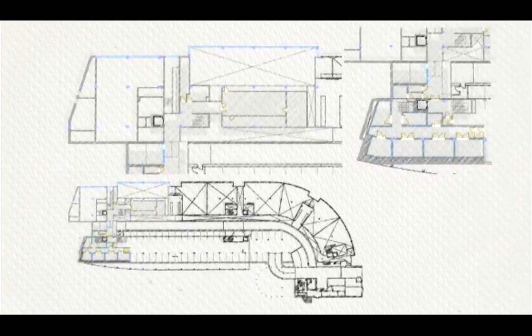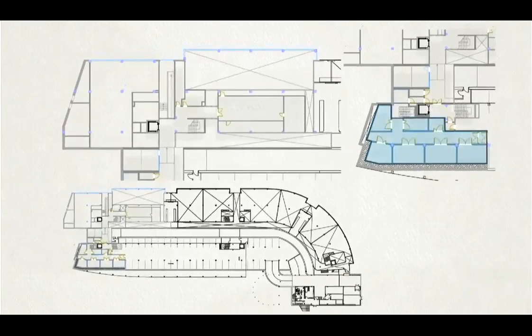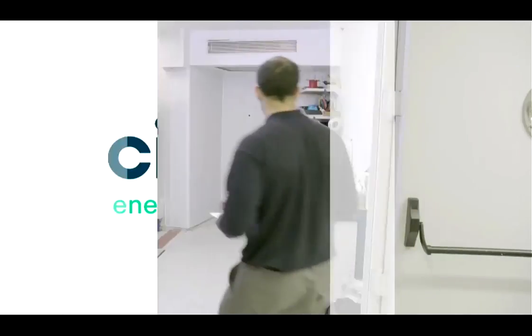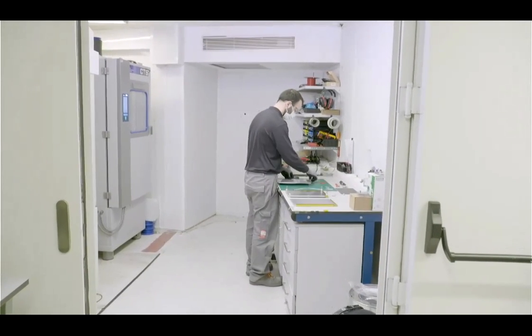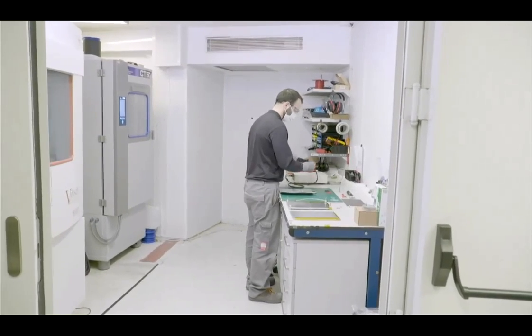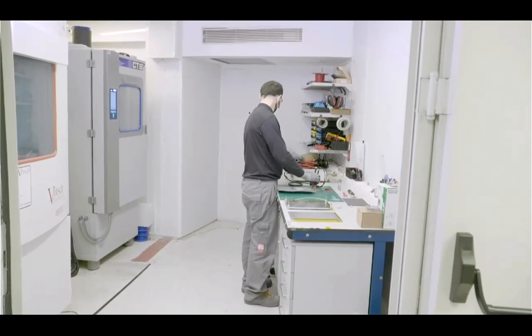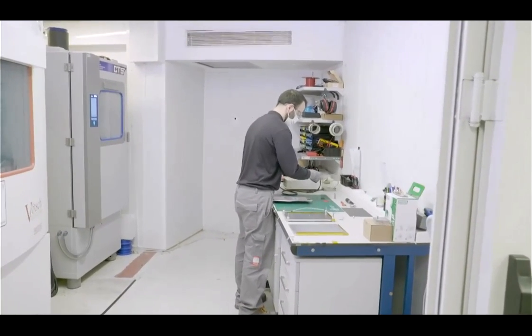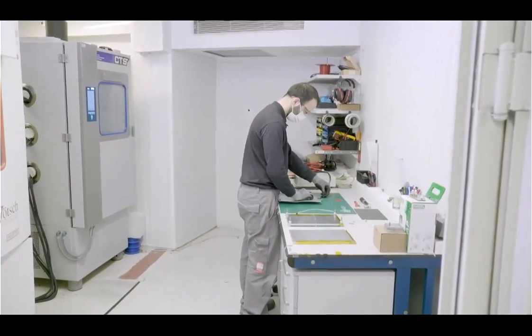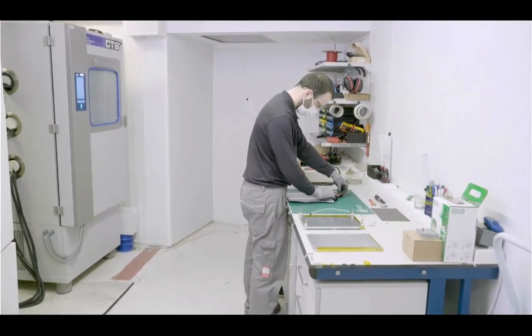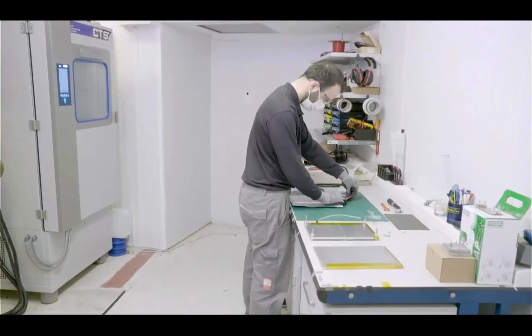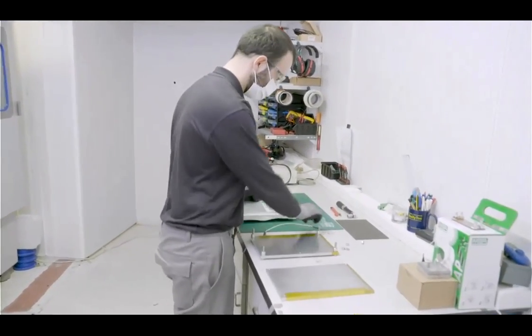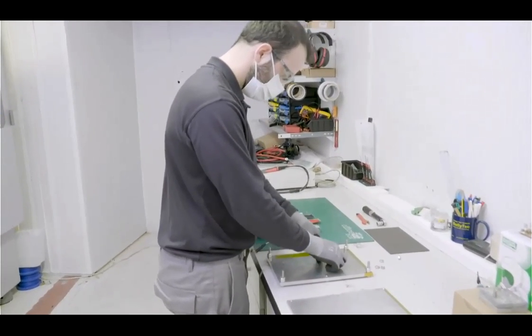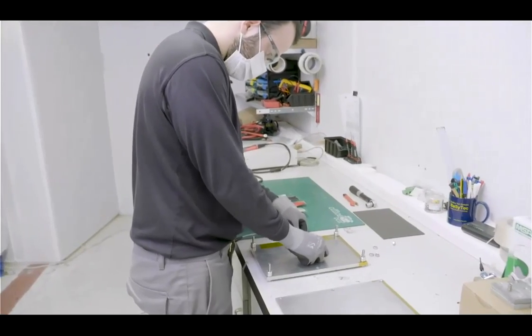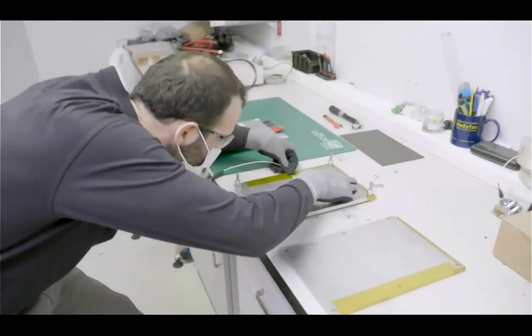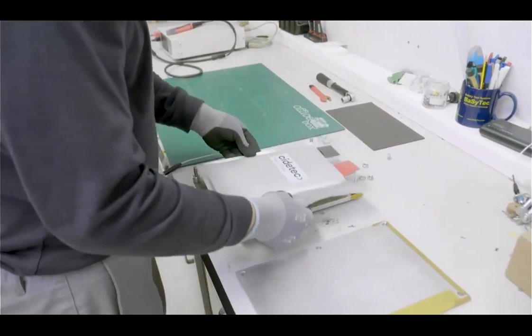Okay, so now we have the cell. So next step is to go out to the testing lab. So first thing is to check that all the assembly process went well, that there is no problem. So for that we have the multimeter, and we measure the voltage and the resistance of the cell. Okay. To do the forming of the cell, we do it between the two plates that you are seeing there. Okay, so my colleague is just putting a temperature sensor, because it is interesting for us to analyze the temperature evolution during the forming.